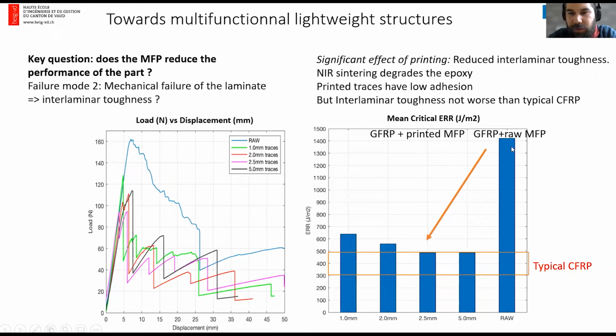Here you can see the average toughness, or critical energy release rate, measured for, I think, 50 millimeters of crack growth. For the raw specimen, we are reaching 1,400 joules per square meter, which is what we would expect for a GFRP composite. While for the printed traces, it is much lower. It's in the range of 500 to 600 joules per square meter.